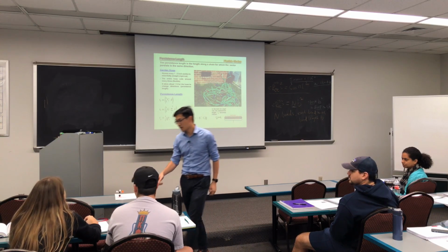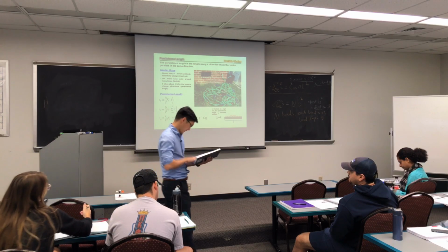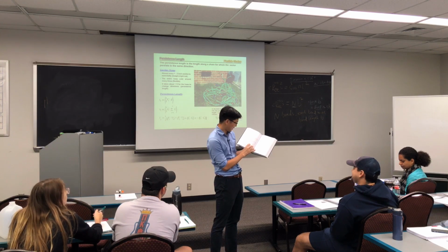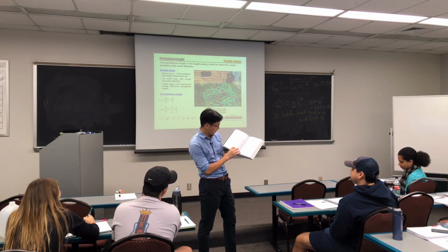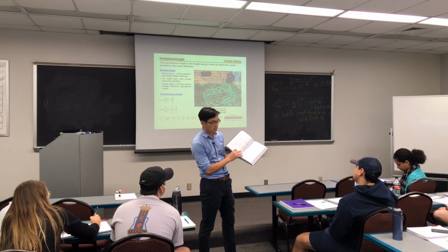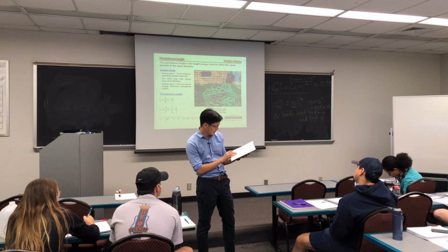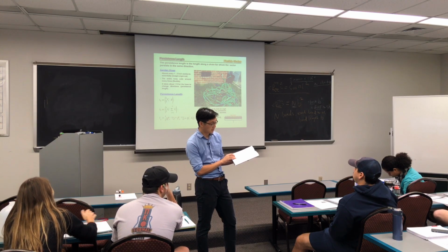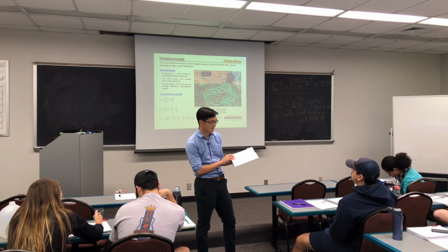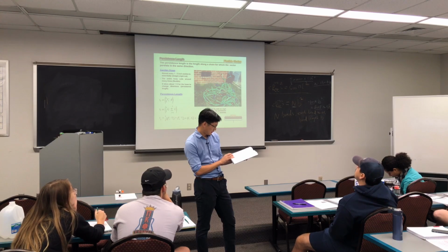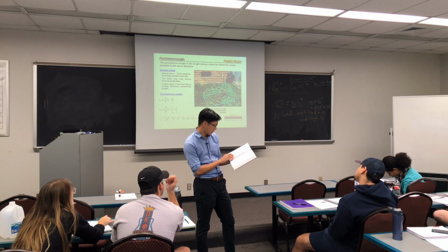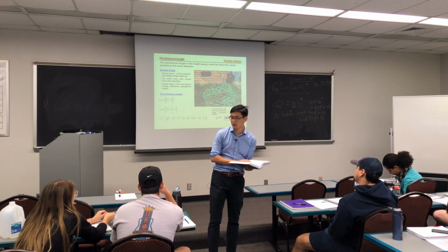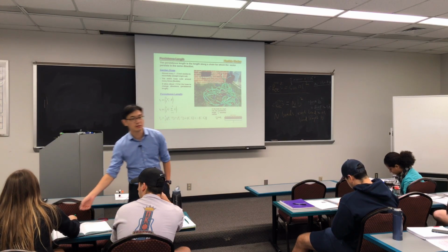If you look at the Sperling textbook, I will give a little bit of a leak for the next class. If you look at persistence length, it's actually already written here in Table 6.1. Lp is described in terms of angstroms here. So most of the polymers are very soft. Polystyrene has a persistence length of about 7.3 angstroms. If you compare to the bond-to-bond length, it's less than 5 bonds. Polyethylene is 5.7. It's slightly flexible, but not terribly short, right? PDMS is 5.3, which is a little bit smaller. But they're all on the order of 5 to about 10 angstroms.